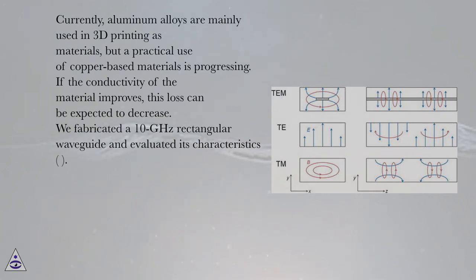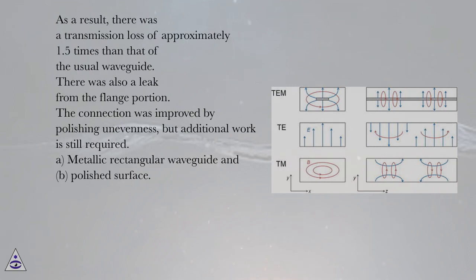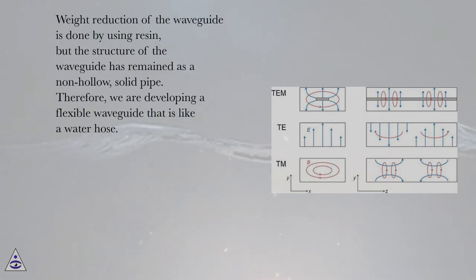We fabricated a 10 GHz rectangular waveguide and evaluated its characteristics. As a result, there was a transmission loss of approximately 1.5 times that of the usual waveguide. There was also a leak from the flange portion. The connection was improved by polishing unevenness, but additional work is still required. A. Metallic rectangular waveguide and B. Polished surface. Weight reduction of the waveguide is done by using resin, but the structure of the waveguide has remained as a non-hollow, solid pipe.